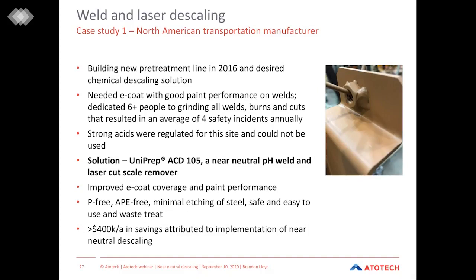Strong acids were regulated for this site and could not be used. So the solution for this applicator was implementation of Uniprep ACD 105, which is our near neutral pH weld and laser cut scale remover for immersion applications.